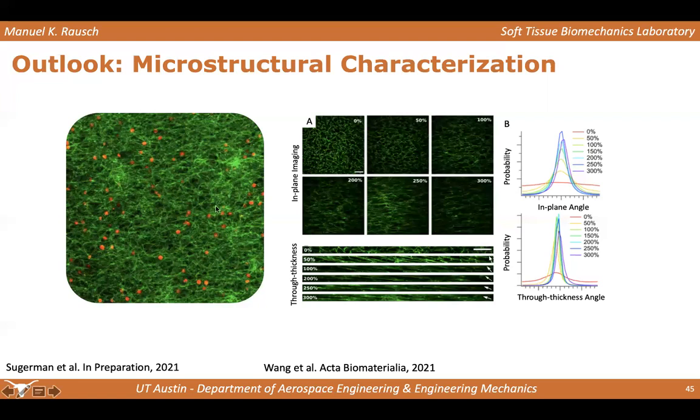And so what you see in green is actually the fibrin mesh, and what you see in red is the red blood cells. So now you can imagine we have this blood clot fluorescently labeled. We can actually do mechanics on this. And so we actually started doing this with my collaborator, where we basically build a little uniaxial tensile testing machine and a little shear tester under a 2-photon microscope, and we can look at the fibrin mesh under deformation.